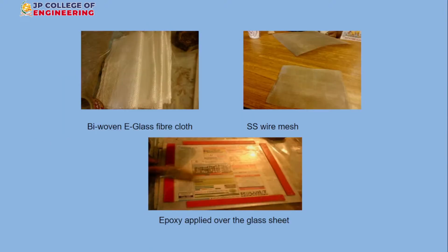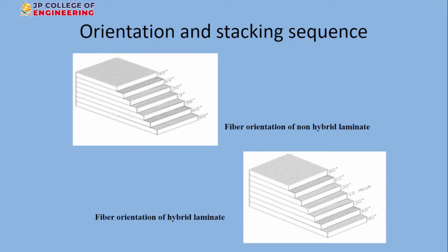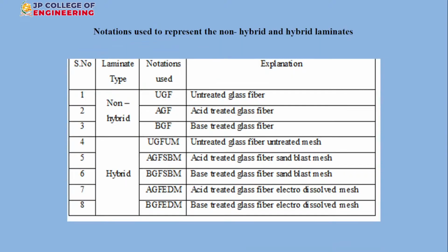Yeah, so this is the way in which I prepared it. We placed these woven glass fiber cloths as 3 layers. The middle layer is a stainless steel mesh, and then we went for another 3 layers of glass fiber woven cloth. This is the 7 layered one. The middle layer we altered, like one with a stainless steel mesh. So 6 layers of glass fiber, and then the middle layer is one.